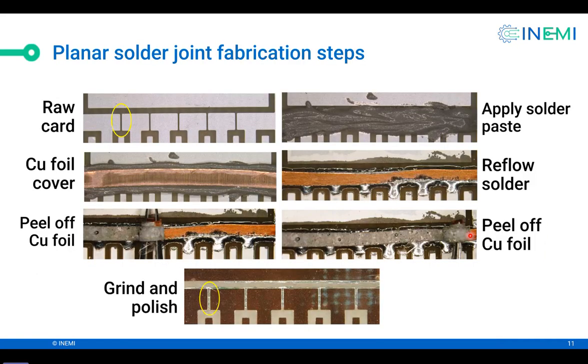Okay, so here is the way we make these samples. The top left picture is a raw card. Now it looks silverish because we have a silver flash over the copper as a solder preservative, so the copper doesn't corrode. It gives us good solderability. We have 5 gaps, 1, 2, 3, 4, 5 gaps in this metallization. And the idea is to fill these gaps with solder that is planar.